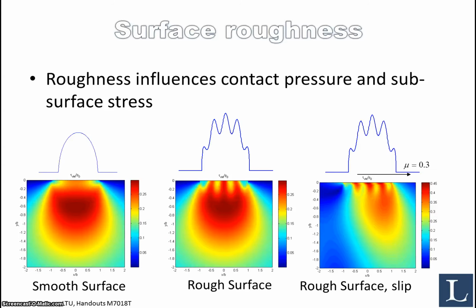And the roughness also plays a role when it comes to contact pressure and subsurface stresses. Here you see three examples where you have a smooth surface to the left, indicating the pressure distribution, and you see the stress concentration in the subsurface here. As you can see, you get a very nice symmetrical distribution of the stresses. Now, if you have a rough surface, on the other hand, you will get a rather different behavior where you have concentrated stresses in the subsurface, and you also shift the position, as you can see, compared to the smooth surface.